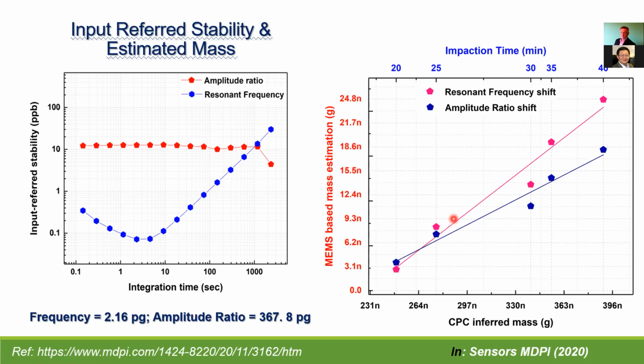which is then compared with the mass indirectly estimated based on the condensation particle counter, which is used as a reference instrument. There are deviations based on the mass, which is calculated for frequency shift and amplitude ratio shift. And these deviations could be because of the spatial sensitivity issues associated with the MEMS resonator, and can also be because of the non-uniform deposition of the soot particles on the resonator surface.